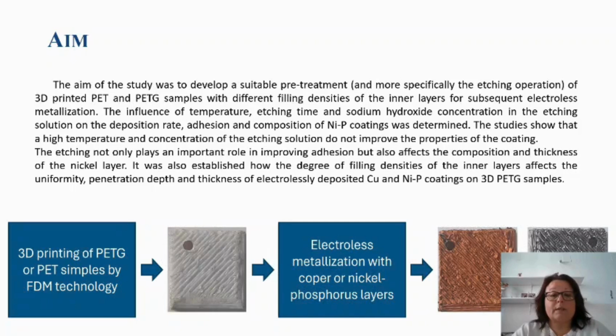The study showed that a high temperature and concentration of the etching solution do not improve the properties of the coatings. The etching not only plays an important role in improving adhesion, but also affects the composition and thickness of the nickel layers. It was also established how the degree of filling density of the inner layers affects the uniformity, penetration depth and thickness of electrolessly deposited copper or nickel-phosphorus coatings on 3D printed samples.